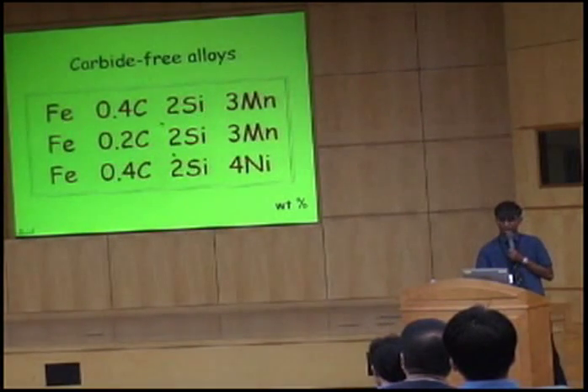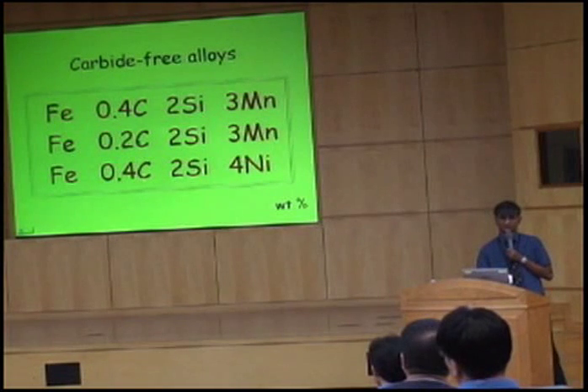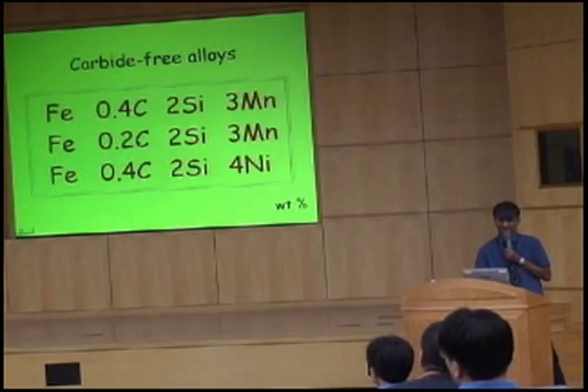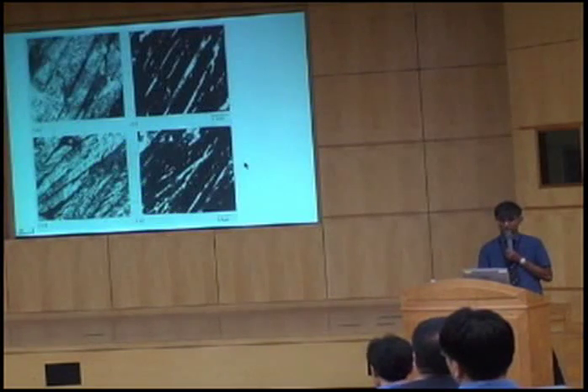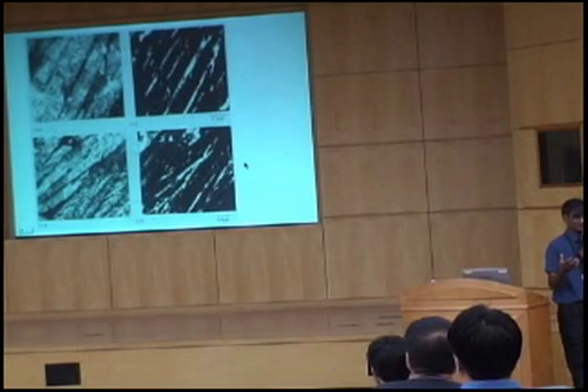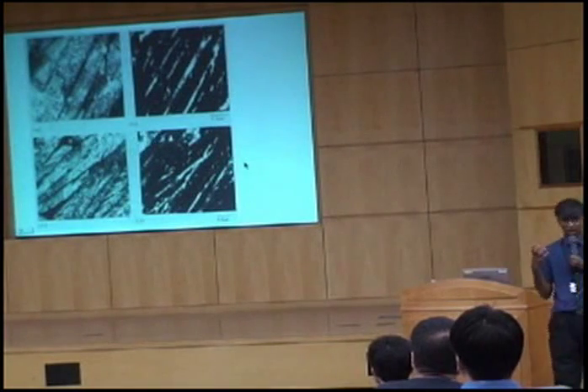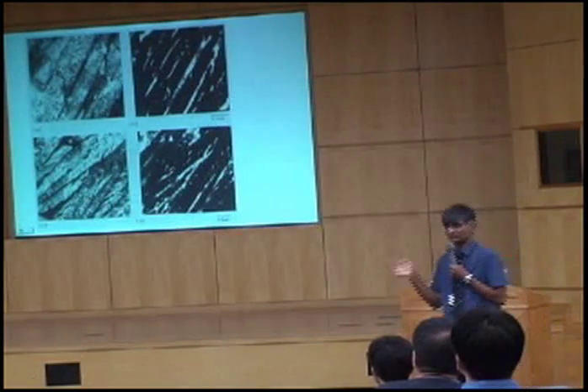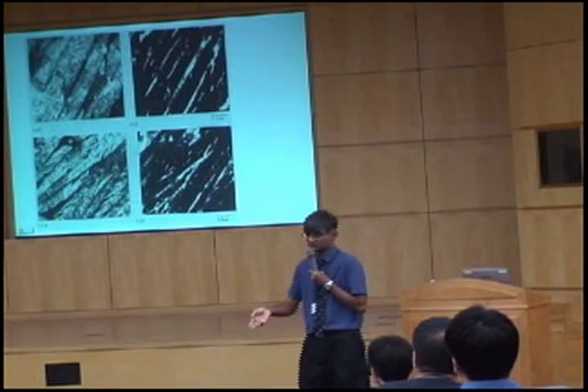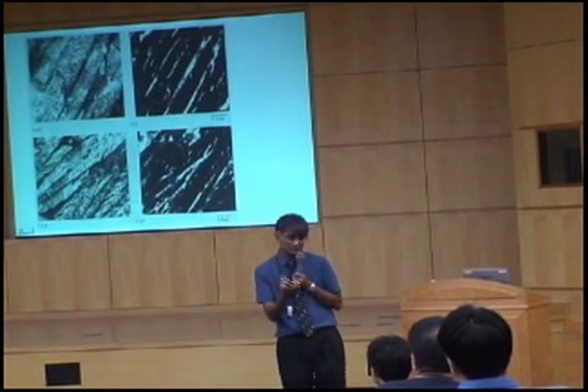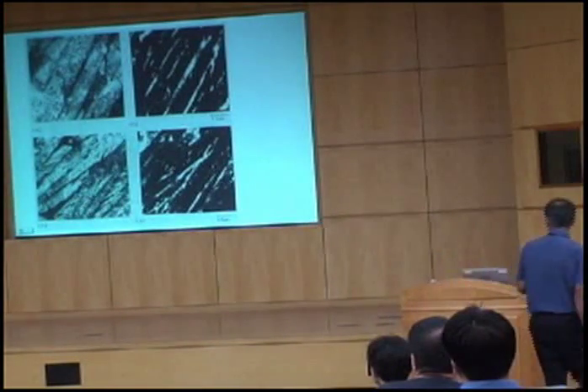So here are the two different alloys. Here we've cut down the carbon concentration by a factor of 2 without losing strength. And in this case, we have shifted the T0 curve to larger carbon concentrations. And here are the microstructures of those two new steels, very nice microstructures with bainitic ferrite and films of austenite. And we've lost the large islands of austenite.